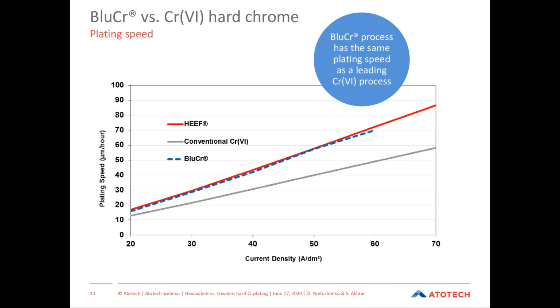The plating speed of the BluCr process at any given cathode current density is comparable to HEEF processes and is much faster than the conventional bath. And as you can see, it's just a linear relationship between cathode current density and the plating speed.